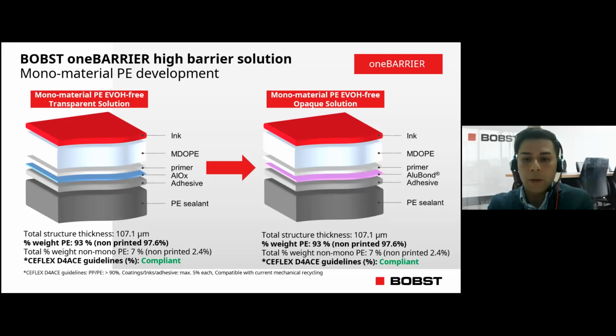Here, the key point when comparing with the previous slide, the previous intermediate solution with MDO-PE with the co-extruded EVOH, is that we can reduce the non-PE material weight by omitting both EVOH and top coat for AlOx layers. The data below the structures once again shows an improvement in terms of compliance with CEFLEX D4ACE guidelines of below 10% for non-PE material weight. Let's swiftly move on to the barrier performance on the next slide of this One Barrier solution.